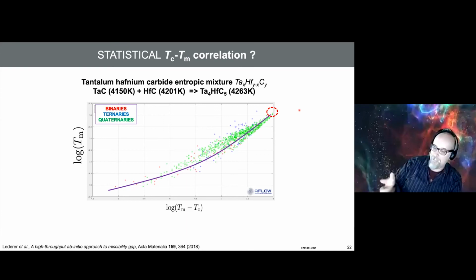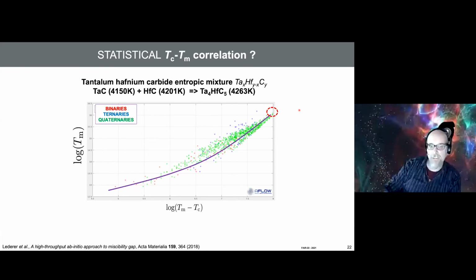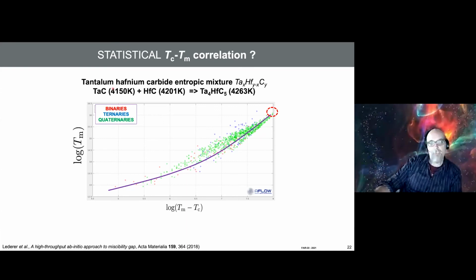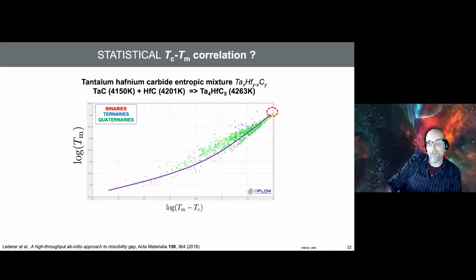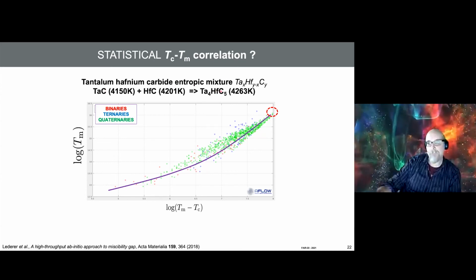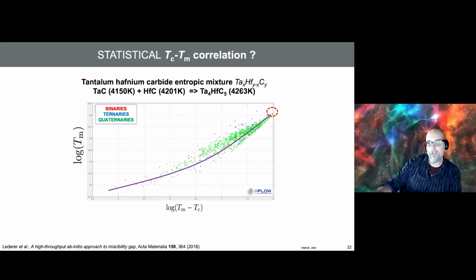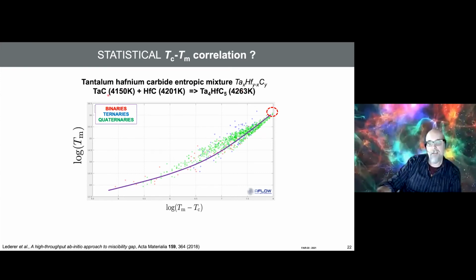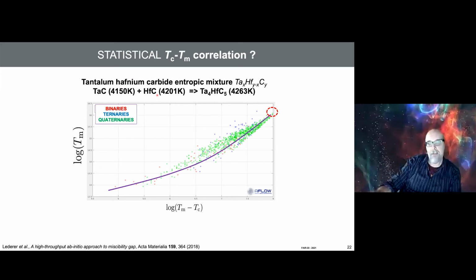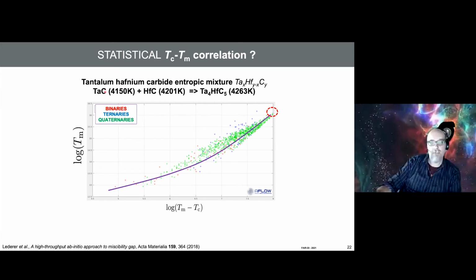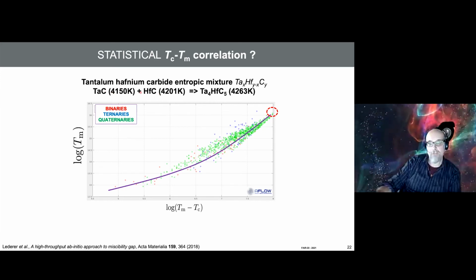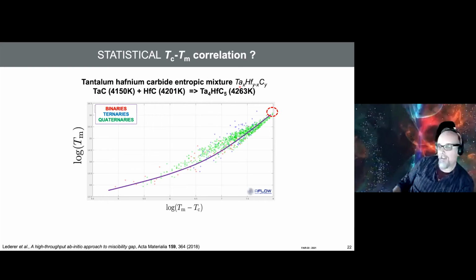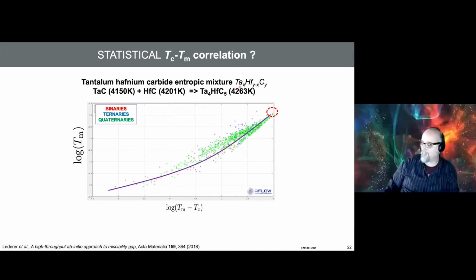So more species and more refractory, but at the same time more mixing. In fact, if you look at the materials with the highest known melting point, which is this one, tantalum hafnium carbide, you see the melting point is higher than its precursors, tantalum carbide and hafnium carbide. So you just get roughly 60, 100K, depends on the experiments.